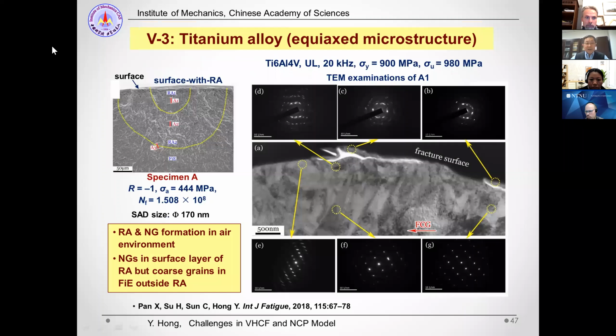And the third result is titanium alloy with equiaxed microstructure. The important thing in this case, under a negative stress ratio of -1, is that the initiation point is very close to the specimen surface, and we examined these parts to reveal the microstructure, which is refined with a kind of nanograin layer. So we can say that the nanograin layer or refined microstructure can be formed in an air environment. This is very interesting.